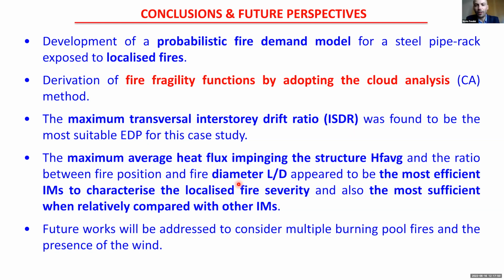And also in terms of intensity measures, the maximum average heat flux impinging the structure and the ratio between the fire position and the fire diameter, L over D, were the most efficient intensity measures to characterize the fire severity, and also the most sufficient relative to the other intensity measures that we used. And we could build up these fragility functions that can be used to quantify the structural capacity of this steel pipe rack. In future work, we would use multiple pool fires and also the presence of wind.